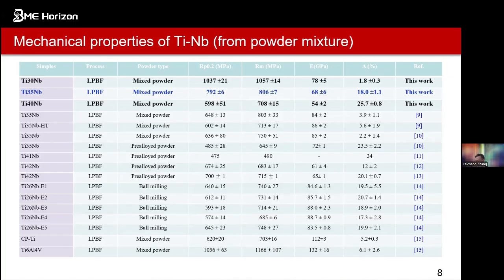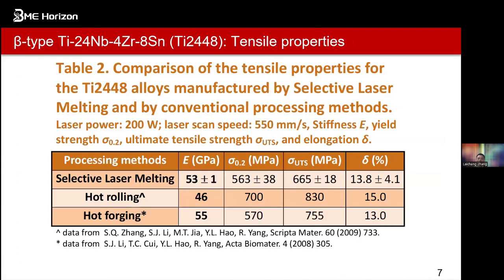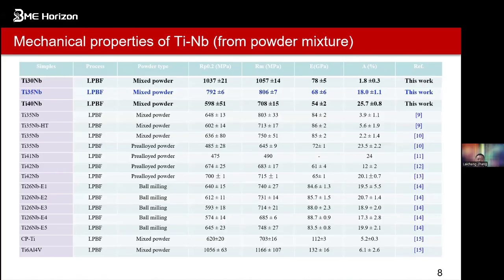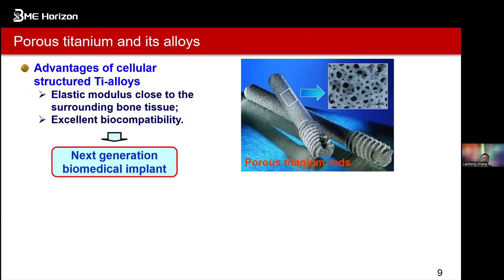But even this one has a low Young's modulus, but still high. We mentioned the Young's modulus of cortical bone is roughly 30 gigapascals, but this is 53. We can still produce titanium parts with a further reduced Young's modulus. That's why this way can produce porous titanium alloys. And of course, this can have a lower Young's modulus, controlled and close to the surrounding bone tissue.